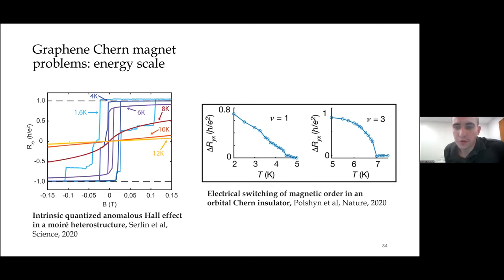So of course, all of these systems are limited in energy scale, right? So the highest Curie temperature Chern magnet that we've realized was this twisted bilayer graphene system, which survived up to 6 or 7 Kelvin. This twisted monolayer bilayer graphene is pretty similar in energy scale. The nu equals 3 state shows that switching survives to 6 or 7 Kelvin. And the aligned molybdenum telluride tungsten selenide only survives to around 2 or 3 Kelvin.